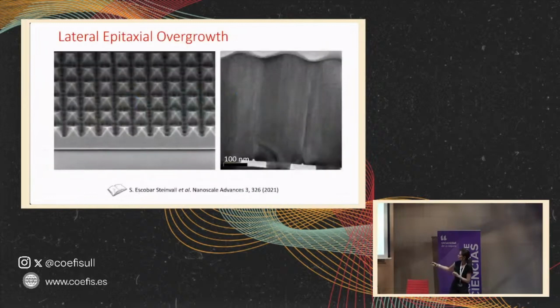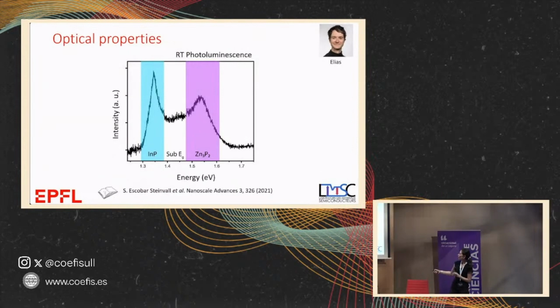If you look at the cross-section of this thin film, you will see there are some grain boundaries here, but the rest is purely single crystalline. And so this is a trick that we have made. If you would grow directly on the substrate without these nanoscale openings, you would be full of defects. If we look at the luminescence of the zinc phosphide, we see room temperature luminescence, and this means that we illuminate with a high energy laser, and the carriers recombine and emit the band gap energy. Having luminescence is the key to know that it's a high quality material. So this was the first step to know that we're on the good path.